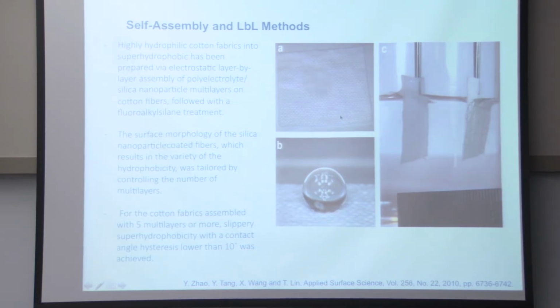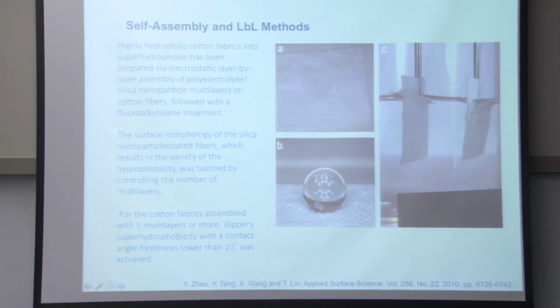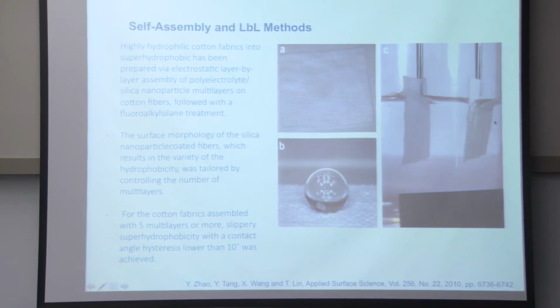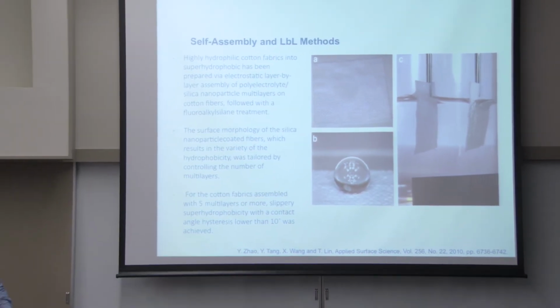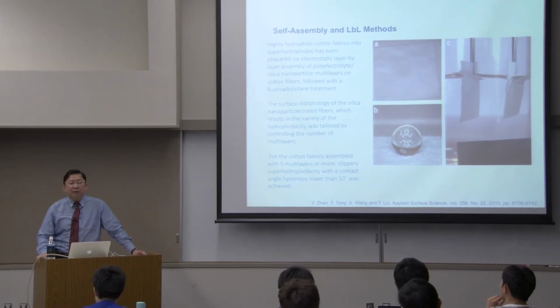You can clearly see here the droplet being unable to form a wetting on the fabric, but more importantly, when you take that fabric and dip it in water, the unmodified fabric has the water contact line going up, whereas the superhydrophobic fabric shows a silver colored texture here, indicating a lot of air bubbles or trapped air during the dipping. That again is a consequence of the superhydrophobic effect.